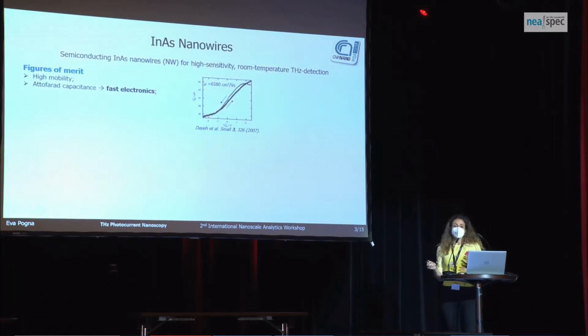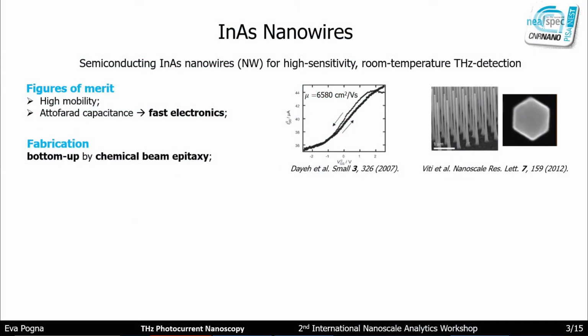I would like to dive into one of the application studies that we have performed in Pisa, about one-dimensional materials. In this case, it consists of indium arsenide nanowires. These nanowires are very promising for detection of terahertz radiation because they have high mobility and very low capacitance, which make them interesting as building blocks for fast electronics. They were prepared in Pisa at the NEST laboratories by chemical beam epitaxy. You can see an example of forests of nanowires.